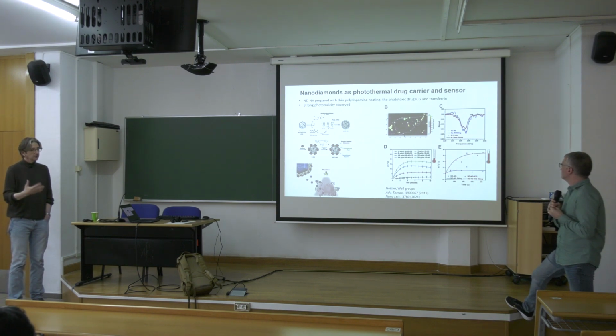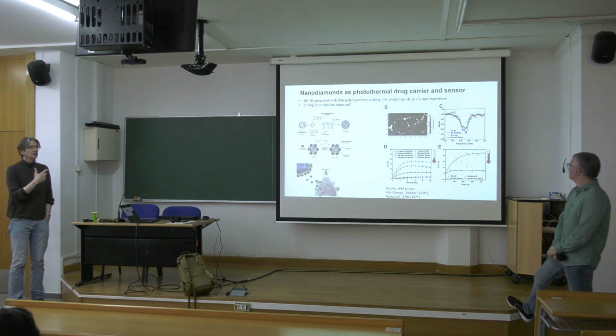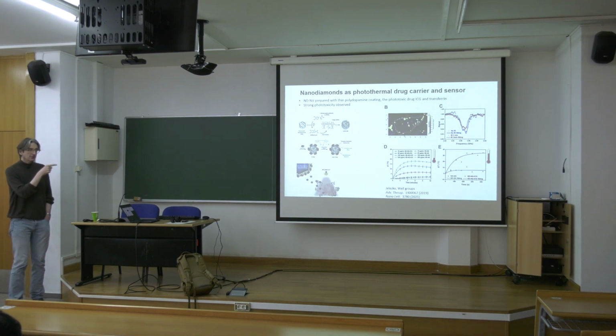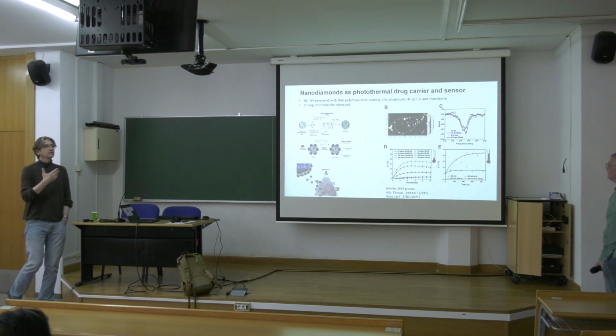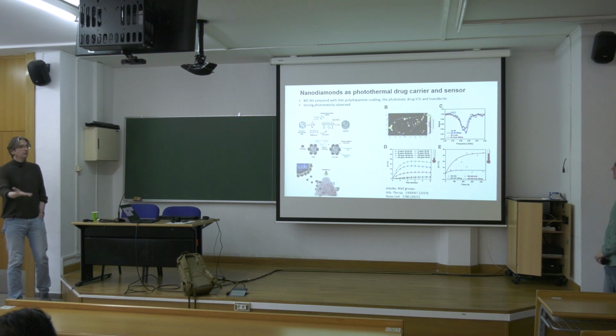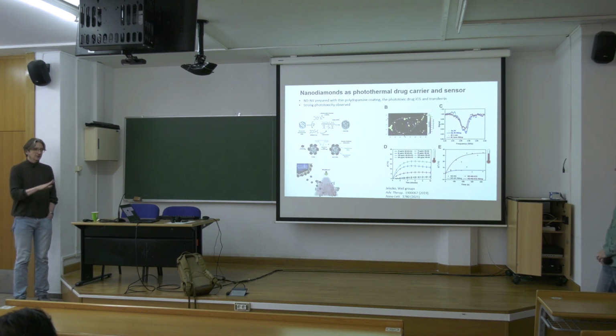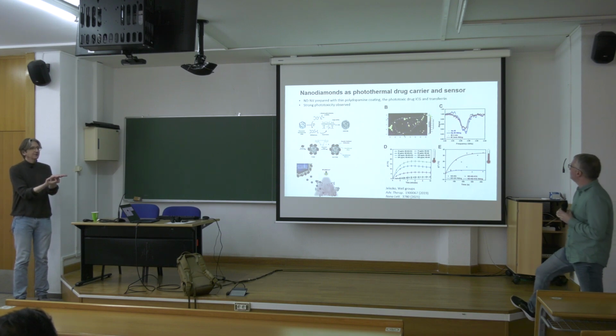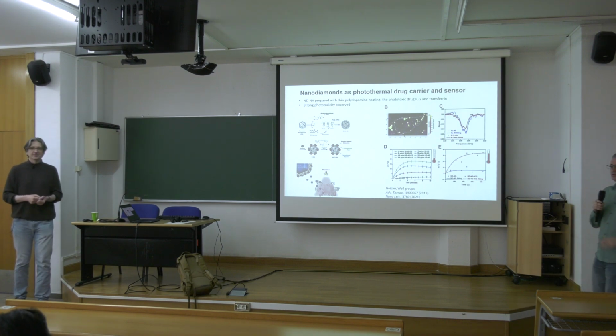So that would be more in treatment cases, but here we wouldn't do thermometry with NV centers. The question that was answered here is to understand when the drug is released, at which temperature, in a cellular environment, and whether it correlates with the action, with the toxicity. That was more for calibration of the action of the drug. The cells were on a glass slide, because of course we need to observe our NV centers, and that was to understand and calibrate the action of the drug. Okay, thanks.